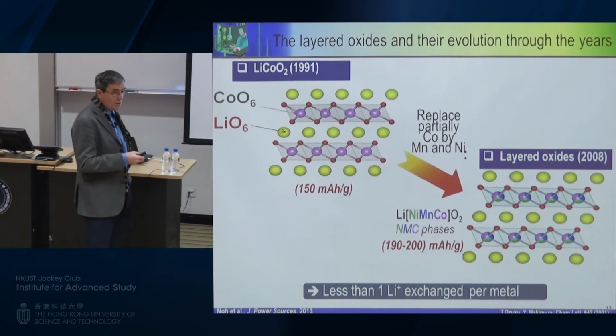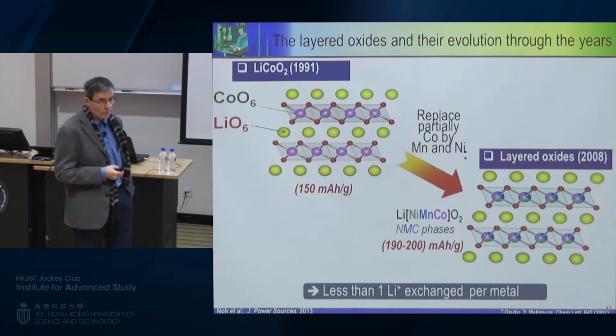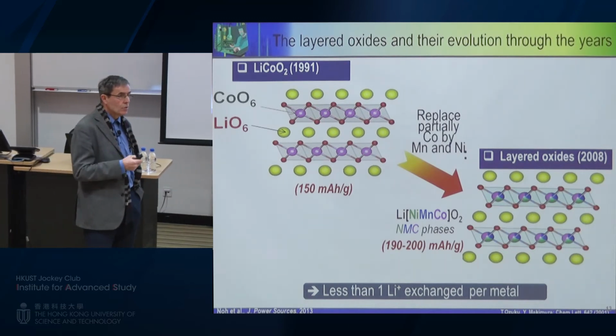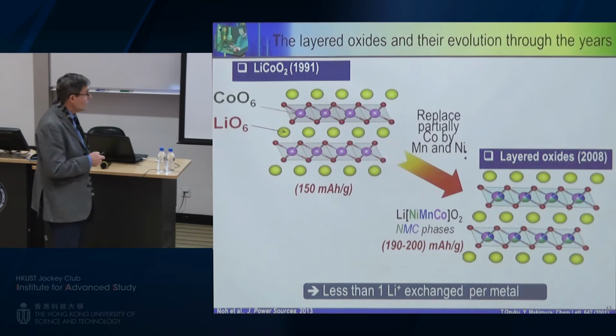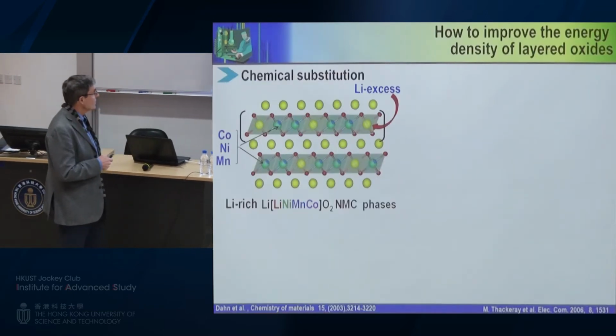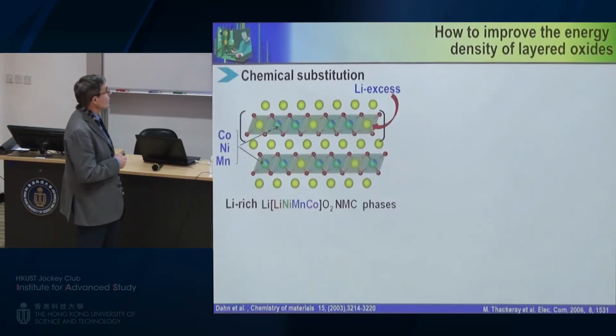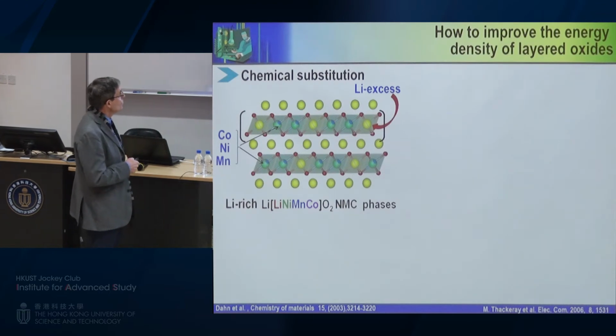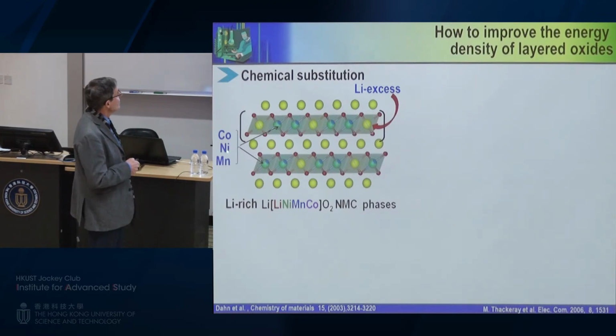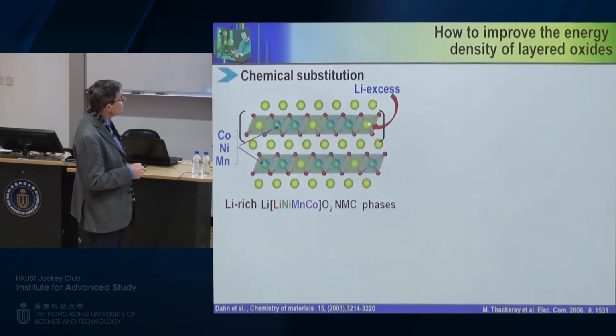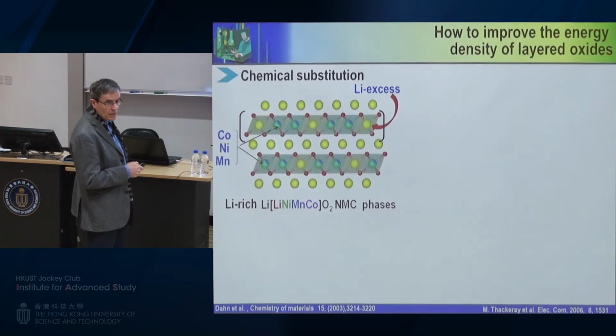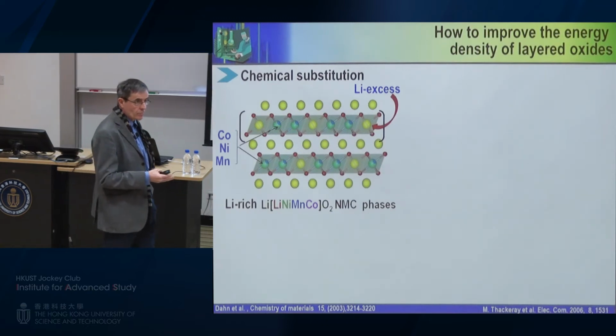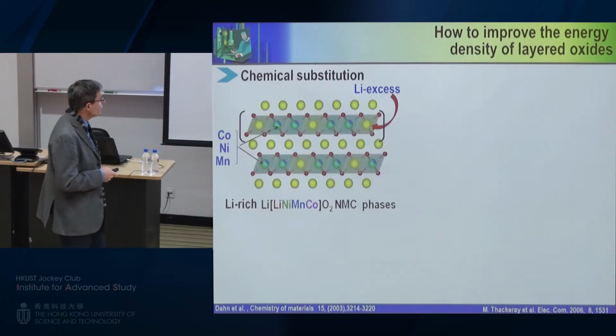You can remove solely one lithium. So the question was, can you go beyond one lithium? Again, different teams, namely Jeff Dahn and Matt Thackeray, continued to do some substitution, and now they not only replace cobalt, nickel, manganese within the metal layer, but look, they put down this yellow atom. And now you have what we call this lithium excess and lithium-rich NMC phase. And this starts the study.